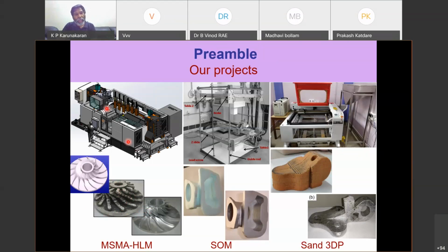So if we hammer after every layer, then the tensile residual stresses will be nullified so that such defects can be eliminated. So this is our flagship project running for the last 22 years or so: multi-station, multi-axis, hybrid layered manufacturing system. Then almost for the last 15 years, we have been working on a 3D printer for thermocol.